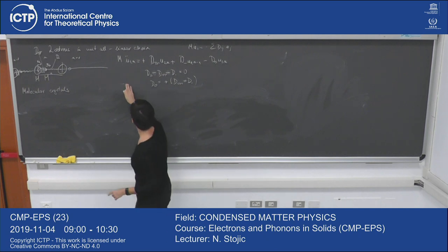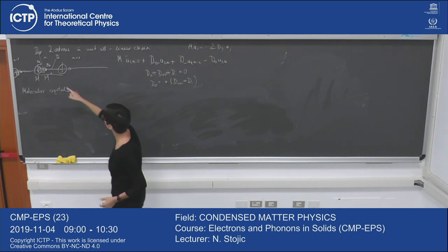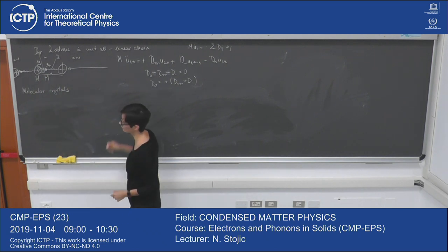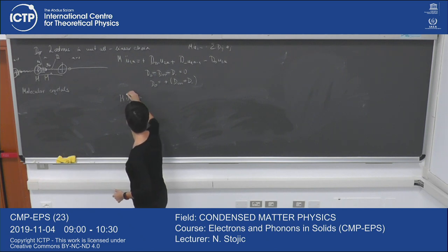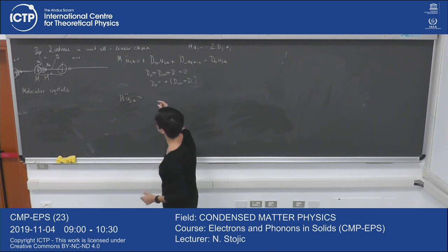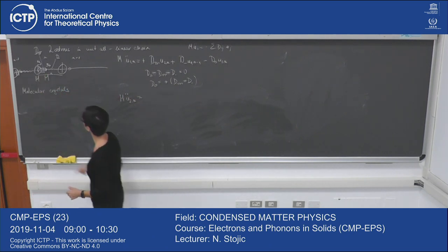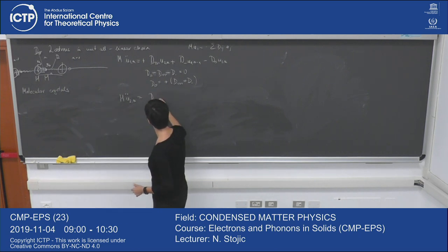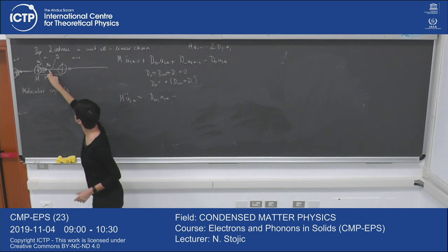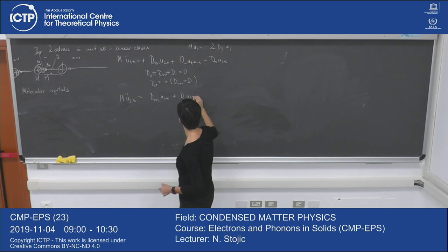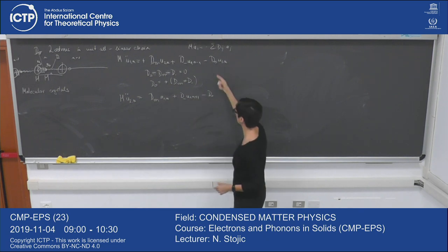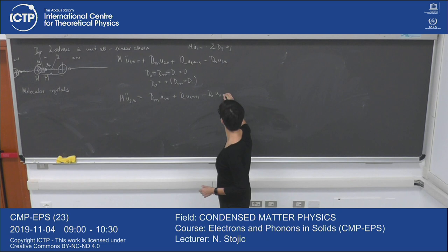And then the same type of equation for the mass 2. Atom 2, in the cell N, is equal: in the same cell N, it has a strong interaction with U1, with the N plus 1 it has a weak interaction, U1, N plus 1, then minus D0, which is the same atom, U2N.